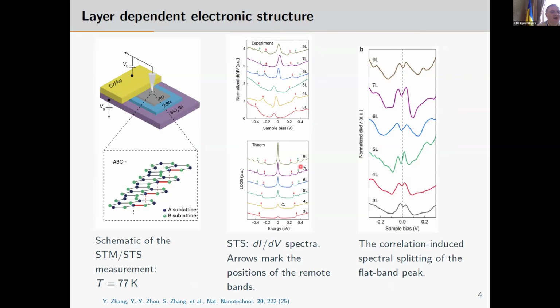And below are theoretical calculations, and the peaks on the left or on the right of the main peak are contributions from the higher bands, which at this stage I completely ignore. What's interesting is that this scanning tunneling spectroscopy shows that this central peak, when temperature is lowered, is divided by 2. So there is a sign of some gap opening, apparently. So this is exactly what we are looking for. This is the reason why this multilayer graphene is so interesting.